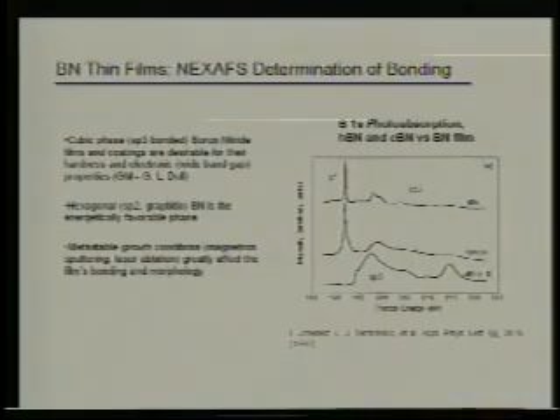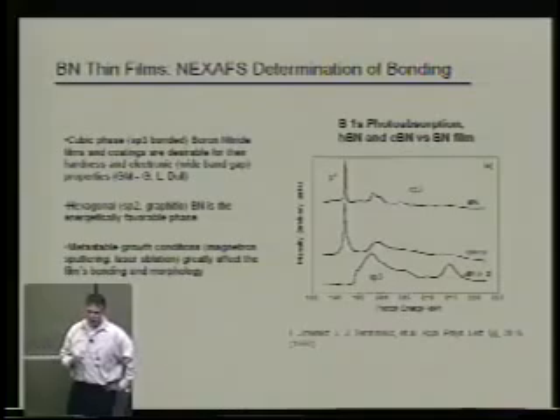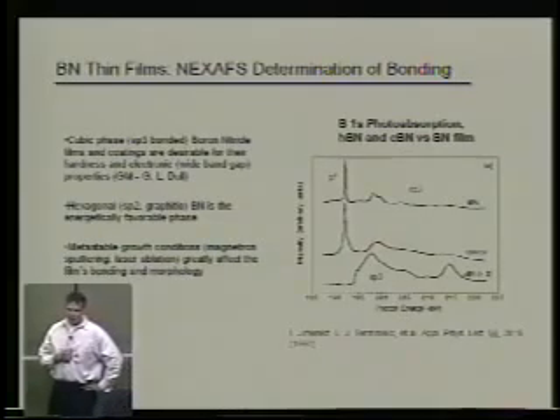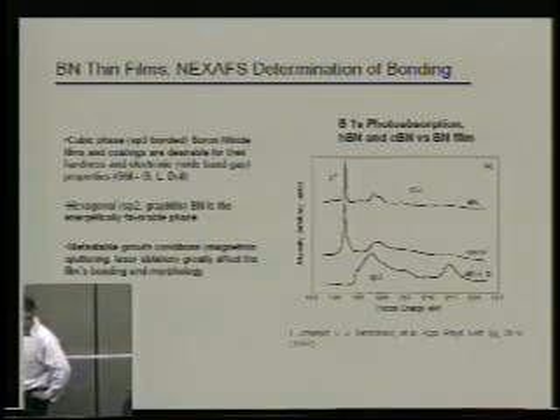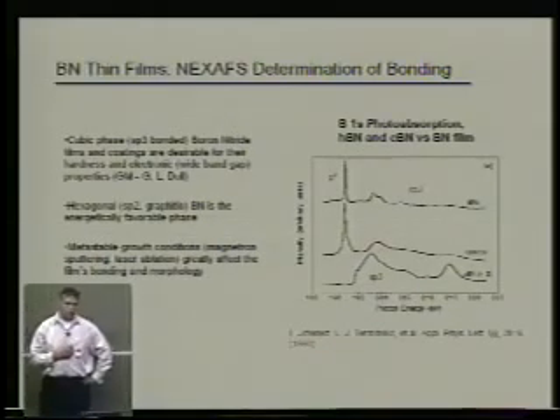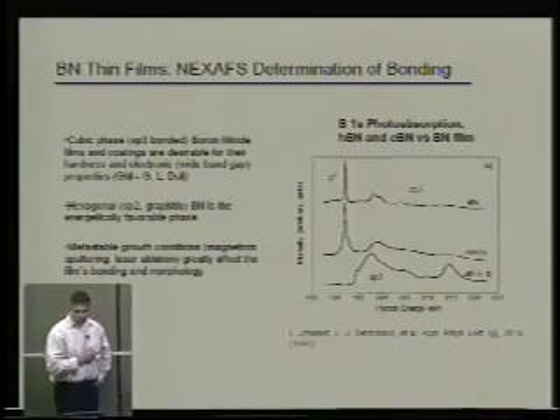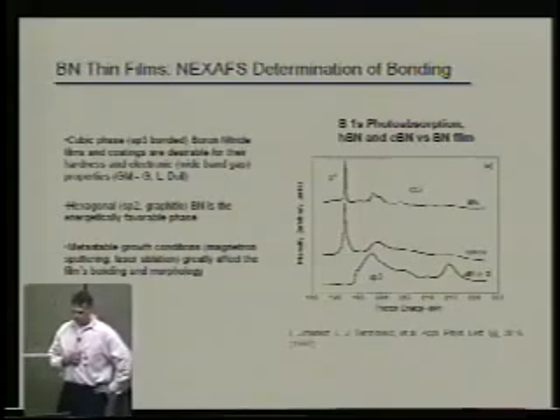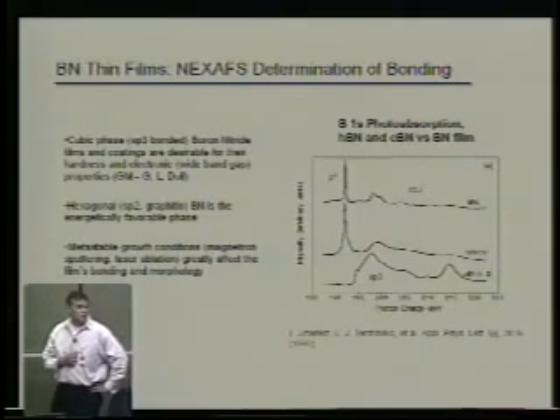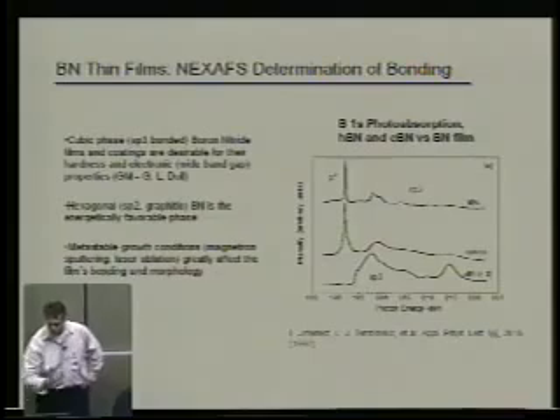So I chose this example because we've talked about how the NEXAFS are actually mapping out the densities of states, or the partial densities of states of the conduction band, or whatever empty states you're looking at. So what I'm showing here is a determination of bonding and the bond order. And I'm showing two examples, a cubic boron nitride and a hexagonal boron nitride. The cubic boron nitride is sp3 bonded, and the hexagonal boron nitride is sp2 bonded. So this is the top curve and the bottom curve.